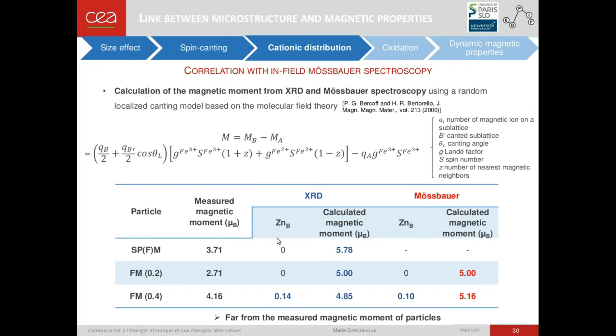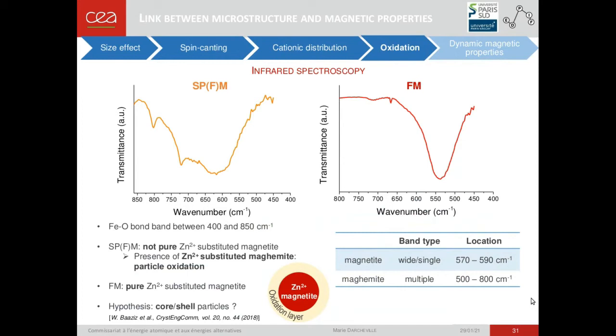This inversion degree in the structure has been quantified through Mössbauer spectroscopy, and the value obtained for zinc localized at octahedral sites is in agreement with that obtained through X-ray diffraction. From these values of cationic distribution, the magnetic moment of particles has been calculated using a random localized canting model based on molecular field theory. However, the calculated magnetic moment is far from the measured one, so it is required to consider another parameter — for example, particle oxidation. I have observed the particle oxidation through the iron-oxygen bond band in infrared spectroscopy.